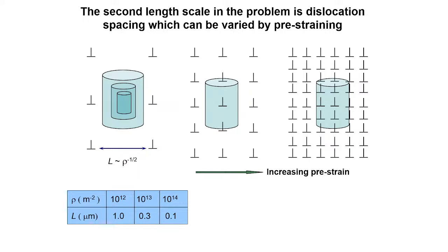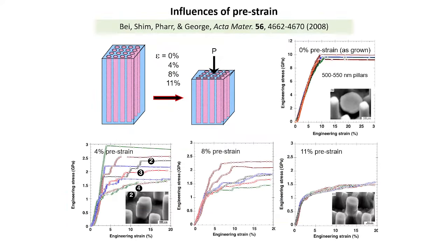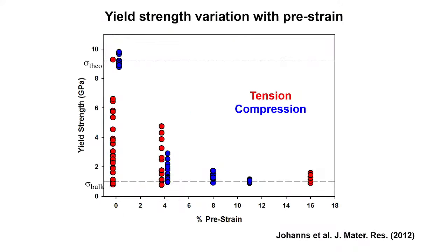So we took material that was initially grown, and then we gave it cold work of different amounts. When you have 0% pre-strain, as grown, all the data fall very close to each other, with a theoretical strength of about 10 GPa. When you have 11% pre-strain, you have so many dislocations in the material that it behaves like a bulk. Again, no scatter here, no scatter there. And then in between, at 4% strain and 8% strain, you get this scatter. So you get probabilistic behavior when the specimen length scales approach the defect length scales, and at the two extremes, you have more deterministic behavior. And this is what it looks like when you compare the tension and compression data. They all behave kind of similarly.